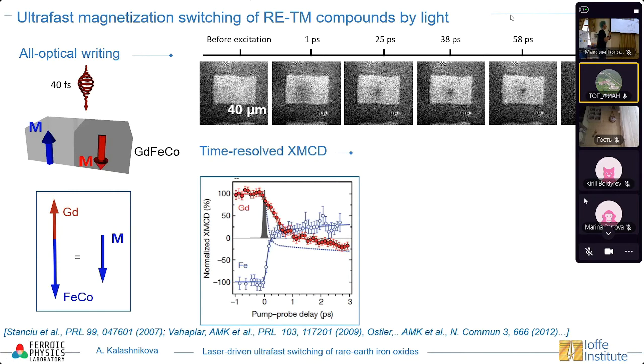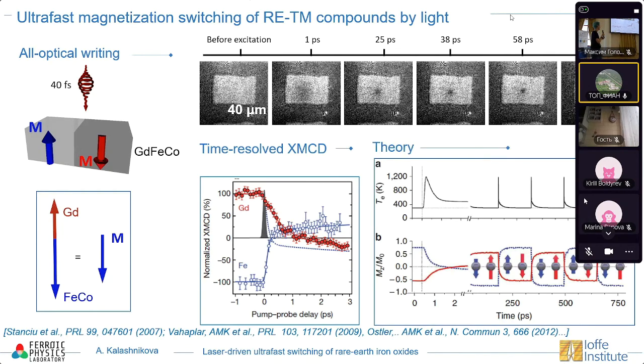But then a very important experiment was performed. It's now a little bit about time-resolved spectroscopy. Basically, it was time-resolved XMCD measured for iron and for gadolinium. And it was shown that when we excite the material with such short femtosecond laser pulses, there is demagnetization in iron and gadolinium, but they happen on different time scales. And apparently, this is one of the key elements of this very exotic and very important switching. It was also reproduced in some theory, but the main point here is that this switching wouldn't be possible if we had only iron or only gadolinium. It is the presence of two magnetic ions which respond differently to ultrafast laser-induced heating that really drives the switching.